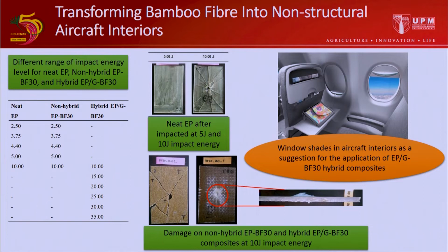The next study, conducted by Dr. Ain Umairah Matshah, was entitled "Transforming Bamboo Fiber into Non-Structural Aircraft Interiors." In low-velocity impact testing, comparison between non-hybrid epoxy bamboo and hybrid epoxy glass bamboo composites shows that the non-hybrid experience multiple cracking and breaking apart, while the hybrid composites only experience perforation and penetration.